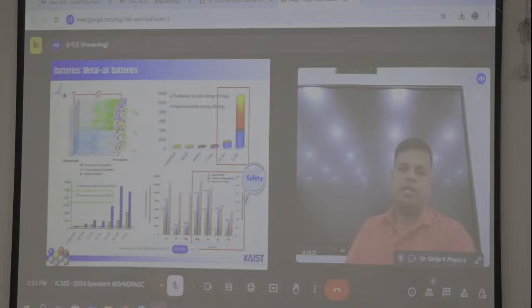So in our case, for the metal there is not much issue, although dendrite formation will be an issue. But when we go for the air electrodes, like air cathode material, there are a lot of issues, especially the transition metals and noble metals people are using, like platinum-based catalysts or iridium or ruthenium-based catalysts. So in order to reduce the cost, we have to make low cost materials. That material should be stable in air media, in the atmospheric media, during the charge discharge process. That is our aim in developing the material. That material should be highly stable and highly performing, with high kinetics towards the ORR or OER performance, like oxygen reduction and oxygen evolution reactions.